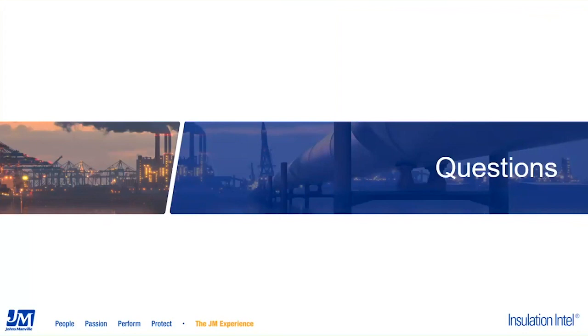If, on the other hand, it is cycling in temperature from cryogenic up to room temperature, that's one of the harshest environments for CUI. When it's cold, it tends to draw moisture in. When it warms up, the chemical reaction of corrosion is exacerbated. The best way to prevent that from happening is through the proper design and installation of a very, very water-resistant insulation system: closed cell insulations, high-quality vapor retarders, proper jacketing, etc. The details of how to accomplish all that are of course way outside the scope or time we have allotted here. But the inquirer could contact JM, and we could give them lots more information on that.